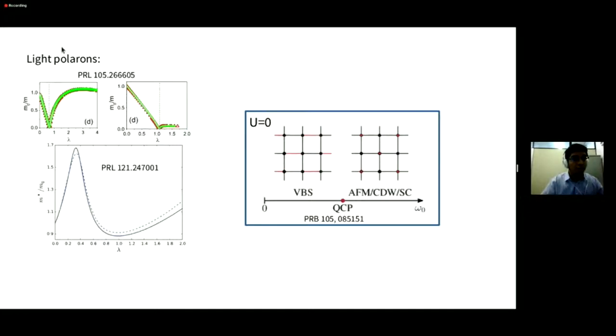The question is simple. How can we obtain high temperature superconductivity? One naive response is basically increasing the electron-phonon coupling. But although increasing the electron-phonon coupling increases the critical temperature, you also create heavy polarons. Your electron is dressed with these phonons, and your quasi-particle is quite heavy. So you start decreasing the temperature instead of increasing. This is why conventional superconductivity cannot be larger than 20 or 30 Kelvin. But if you can have light polarons, then probably you can have high temperature superconductivity. And this is what these people are presenting here in this paper, the possible occurrence of light polarons.